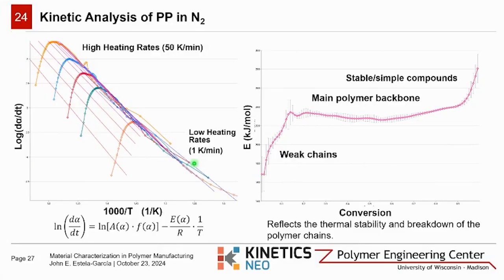By examining the activation energy across the conversion range, we observe three distinct regions. We see a low activation energy region, and this corresponds to the breakdown of weak points in the polymer structure, such as chain ends, branch points, regions that have structural defects. And these weak points require less energy to initiate decomposition, making them the first to degrade during thermal stress.